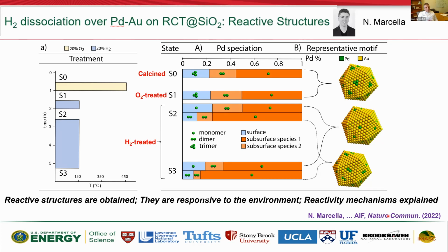In the part which is still sort of not quantitative, I wanted to show this analysis that my student Nick Marcella did, where we can link the experimentally measured coordination numbers by machine learning XANES to possible structural motifs representative of these numbers. Of course, these coordination numbers are just average information. So if you have some distribution, they may still end up to be the same, so it's a representative, not exhaustive search. But at least it gives us some speciations that are typical in this material.